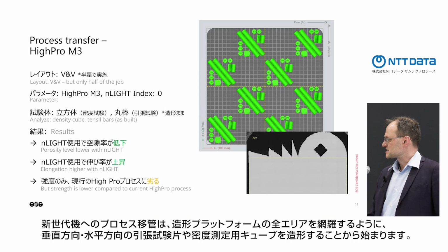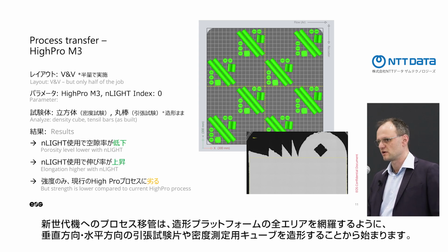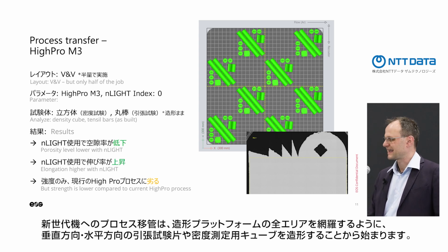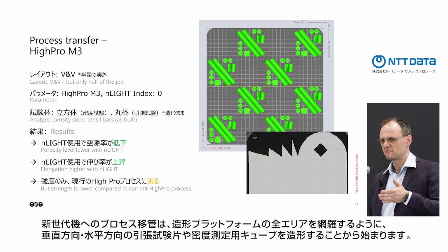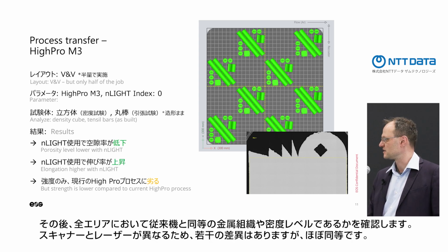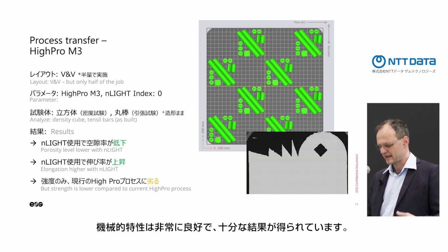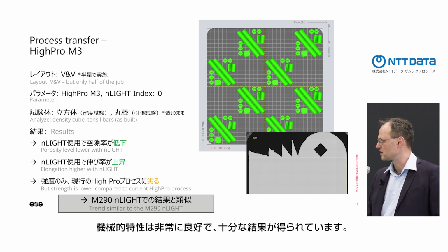The process transfer starts with building tensile specimens in all areas of the build platform, horizontal ones, vertical ones, density cubes, and we check: can we have a comparable microstructure? Are the density levels in all areas of the platform comparable, and so on? And the answer is yes. They are a little bit different because the scanner and the laser are different, but they are very comparable. So the mechanical properties are good, and they are good enough.